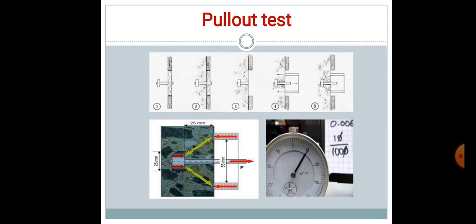How does it work? The pull-out test is achieved by measuring the force required to pull a 25 mm diameter steel disc cast in concrete. The steel disc is embedded 25 mm in depth in fresh concrete at the time of concreting. A pull bolt is attached to the steel disc. After the curing period, the steel disc is pulled until failure of the concrete occurs. As the steel is pulled, a rough cone-shaped fragment of concrete is extracted and the pull-out force is measured.